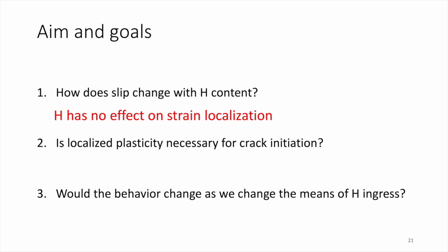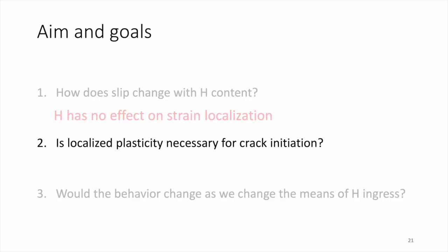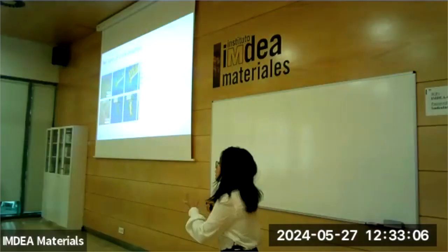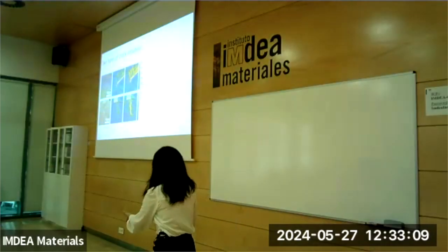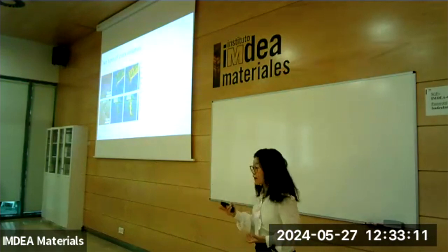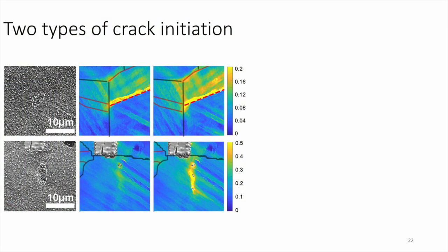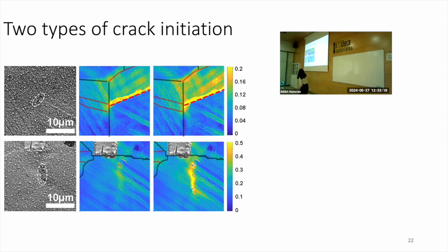Okay, let's move on to the second part, which is: is localized plasticity really necessary for crack initiation? We take a closer look into our material, and we see there are two types of crack initiation event. One with nearby slip, the other without. In this figure, red lines represent twin boundaries and black lines are the non-twin grain boundaries. The first strain map is right before the crack initiation. The second strain map is at initiation.